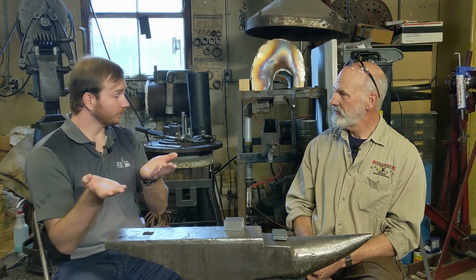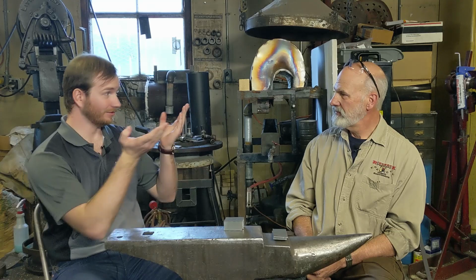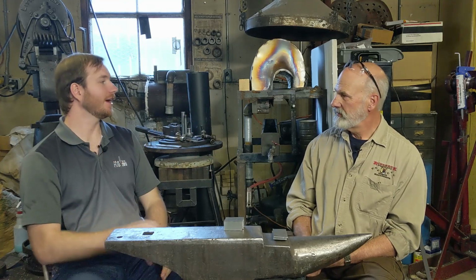How do I heat treat this? How do I determine what the heat treat is? Because I have 2 different possible heat treating routes. How do you determine how to actually perform the heat treat on a Damascus blade? Well, we look at the steel that takes the quickest shock heat treating.